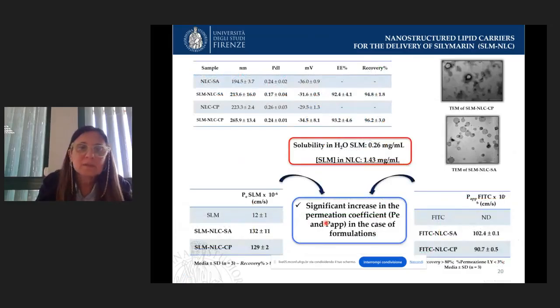We characterized the carrier from a physical and chemical point of view. In particular, here is the carrier, the NLC with stearic acid loaded with Silimarin. We obtain a dimension around 200 nanometers. This formulation is for oral administration, as the dimension is good for oral administration. This system results homogeneous, PDI less than 0.3 indicates a homogeneous system, and also the zeta potential, the potential around the nanoparticles, around the NLC, is high, and this stabilizes the system, the colloidal dispersion.